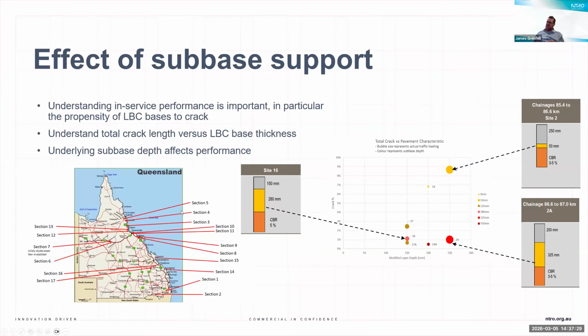Another aspect to this was to try and understand how and where these materials have performed well and where they perform badly in the field, to understand any guidance around how they should be used. So we looked at a number of different field sections in Queensland, looked at their long-term performance, and were able to correlate where they'd performed well and where they performed badly, which helped to produce some advice around the amount of unbound granular subbase support they should require to perform well. You can see on this graph that the materials that have performed well tended to have a lot of unbound granular subbase support, whereas up here, a section that's performed badly in terms of the percentage cracking over its lifetime was seen to have very minimal subbase support over a low CBR subgrade.